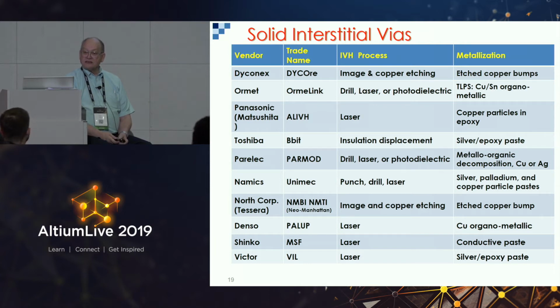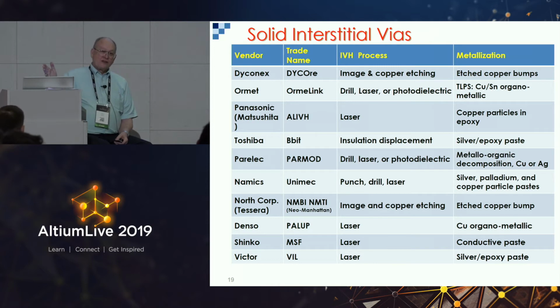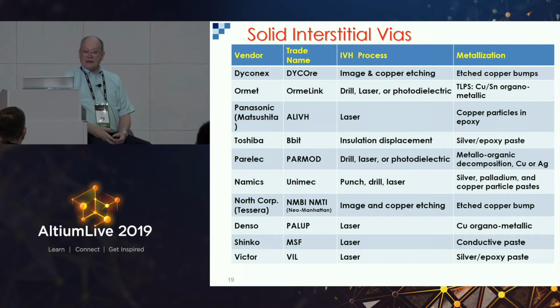Then there's solid interstitial vias. This is part of the 2.5 to 3rd generation. What they did is they got rid of electroplating because of the environmental green aspect. And they went to making vias out of paste. Now, the nice thing about making a via out of a paste is that you can ignore aspect ratio. So you want a 30-to-1 aspect ratio? You physically force the paste into a laser drilled hole until you have a 30-to-1 aspect ratio. Nobody can electroplate that. But they can make the board because they're not using liquids, they're using a paste.